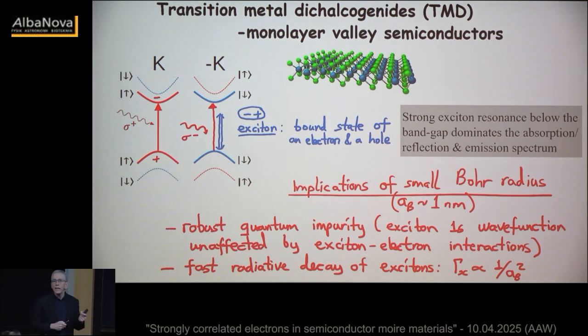But the main point is that the large momenta here are the magnitude of the momenta associated with this circular motion. Because of this, the optical selection rules tell us that, say, in K valley, we can do excitations using sigma plus light, and in minus K valley, we can do it with sigma minus light. And because the electron and hole interact, this is pretty much true for all semiconductors. Here it's even more true, I'll come to that. When we do an optical excitation, the electron binds to the hole that it leaves behind and forms an exciton. So if I shine sigma minus light, I form an exciton in the minus K valley and vice versa. And this is independent of the spin.